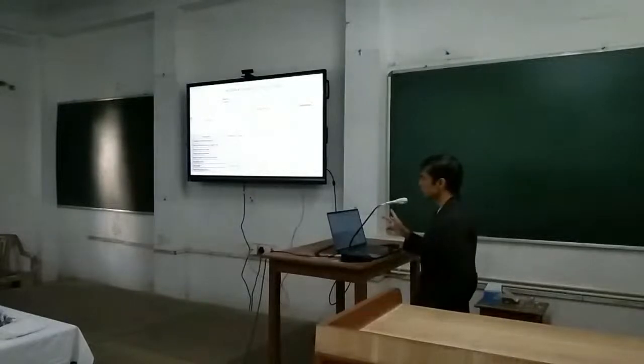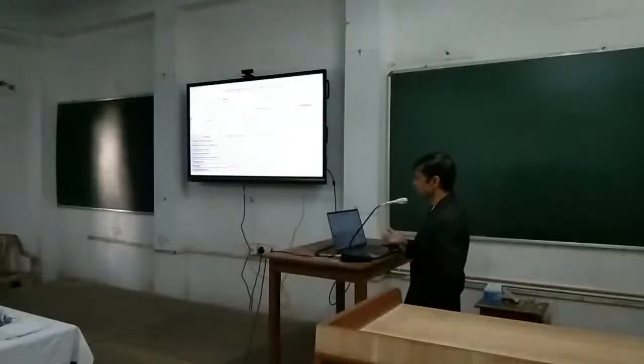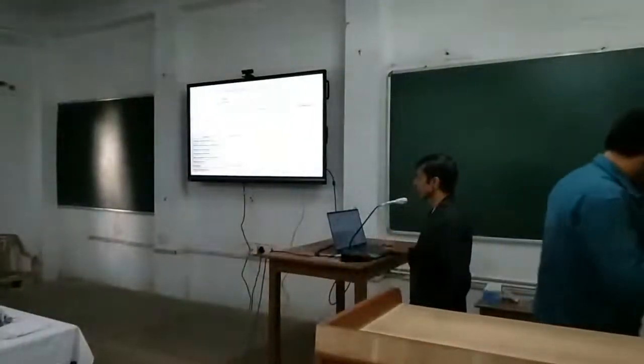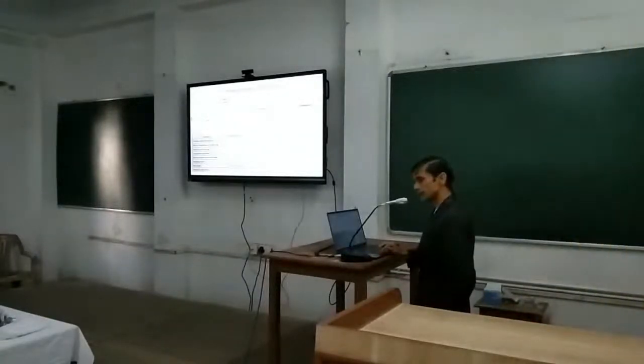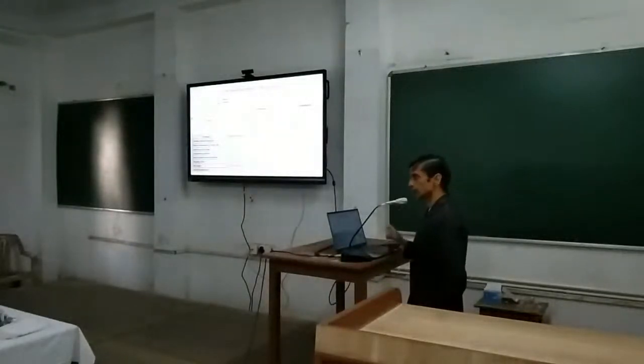There are two aspects. If you machine ductile materials, in micro grinding you have a very small depth of cut, table feed of course is at your hand, and very high velocity. Altogether what happens? The grit penetration depth is low, and specific energy consumption increases. So from conventional grinding to micro grinding, the problem is that the grinding grits interact with a smaller volume, and for ductile material that's a problem. But for ceramic materials, if you increase the velocity, you have an advantage. That means you can machine the ceramics in the ductile mode.